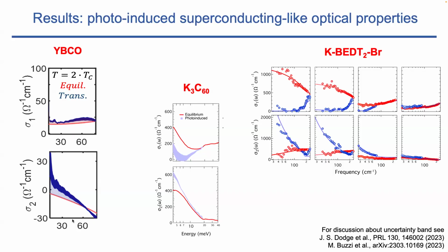This is potassium doped C60. You start in the metallic state. This is the Drude. You open a gap. In this specific case, there's been a lot of discussion. It turns out that the size of this gap is a bit negotiable. But nevertheless, regardless of how you fit the data, you find gapping and divergence in sigma 2. And in YBCO, which is what I'm going to tell you about today, you will find gapping, not gapping, depending on whether you look along the insulating C-axis or the AB planes, but you definitely find this divergent 1/omega response of the conductivity. So these are all features of the superconducting-like state, and I'm going to tell you a little more what I mean by that.